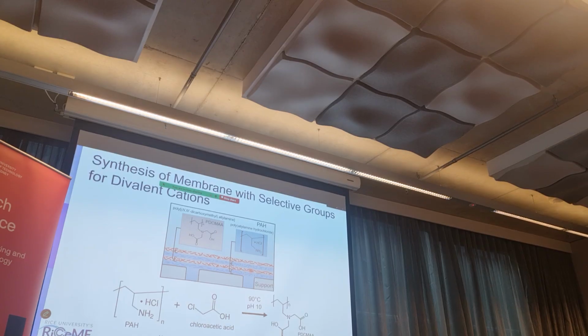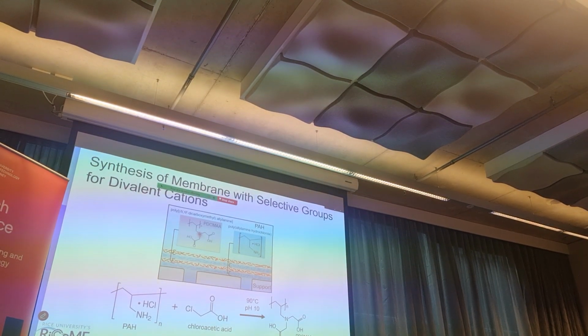And this is just PAH, a positively charged polyelectrolyte, so we create a layer-by-layer membrane. Unfortunately, this polymer is not available commercially, so we need to synthesize it using the method here, like a cooking recipe. Then we do layer by layer, positive, negative, positive, and end up with a negative layer with this functionalized, highly selective, complex functional group.